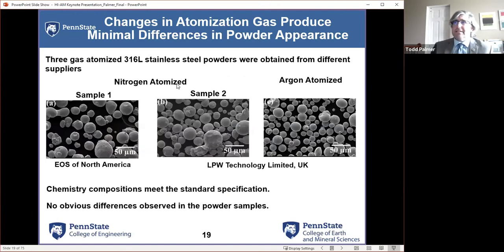In this case, this is getting a little more into one of the studies that we've been doing, and we're getting ready to try to publish a lot of this material: what happens if I change the gas that I atomize with? It's a common consideration, primarily up front, as a way to adjust my composition. I may change atomization gases as well from a cost perspective. Nitrogen is a whole lot cheaper than argon. If you've bought argon recently, you start to see, and I bought a lot of argon to build a lot of the components that we built, I will tell you that it gets costly pretty quickly.